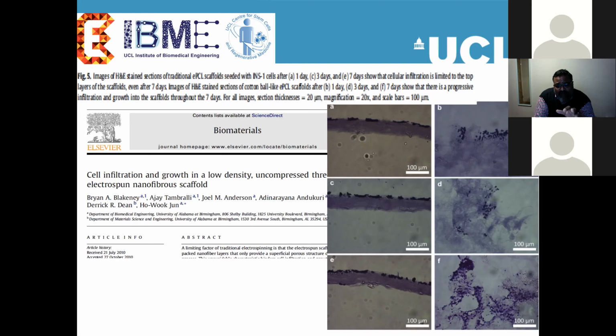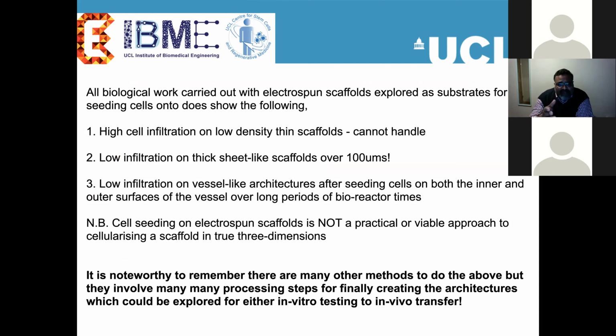And added to that, if you layer a bunch of cells on the first layer of gauze, if the piece of gauze or scaffold is thick, the next bunch of cells that you deposit on it through manual or automated deposition is not going to go through, because once cells deposit on these scaffolds, they spread. Once they spread, they start blocking the actual pores. So infiltration is a problem, and there are various other issues here.